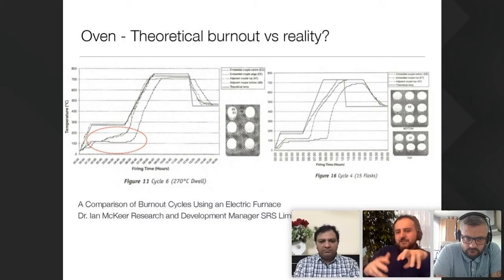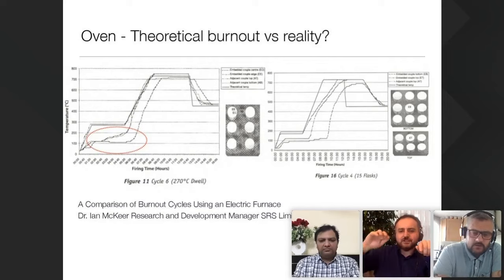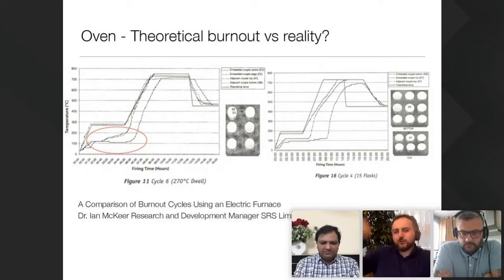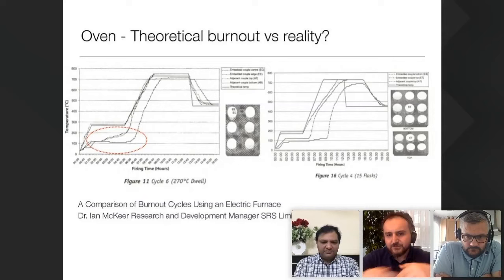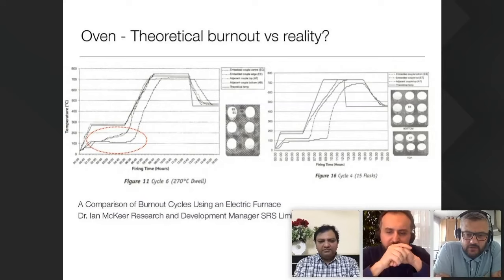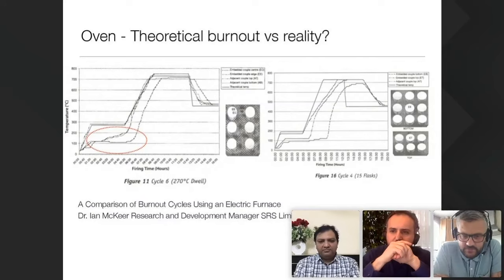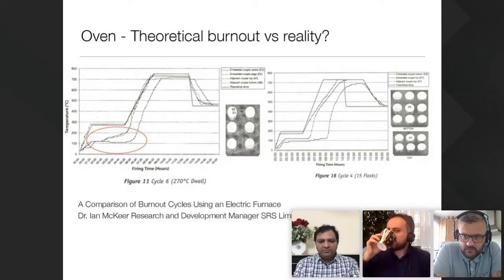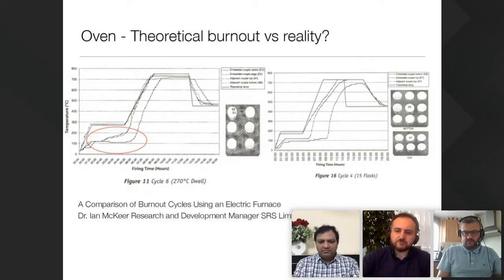In other words, it's not metal inside the investment. If you reach a certain temperature inside the investment, it takes time also to reduce. You cannot just switch off your oven and say, okay, now I go back to 500 degrees - you cannot do that, right? That's why we say once you come down to your casting temperature, always wait a minimum of 1 hour, so the center, the core of the flask, harmonizes with the temperature that you've set it to.